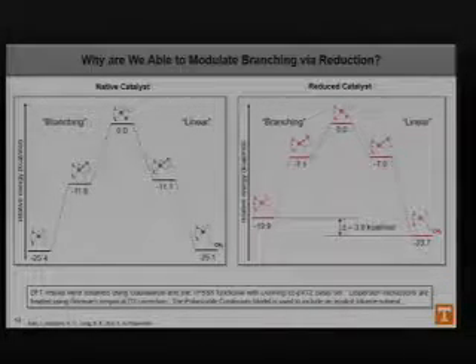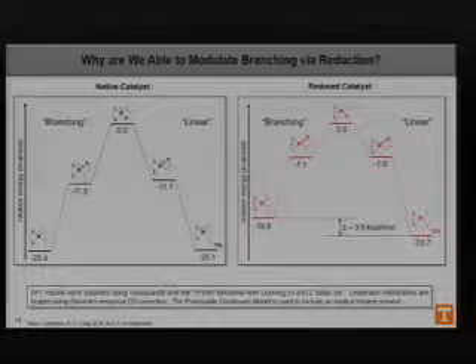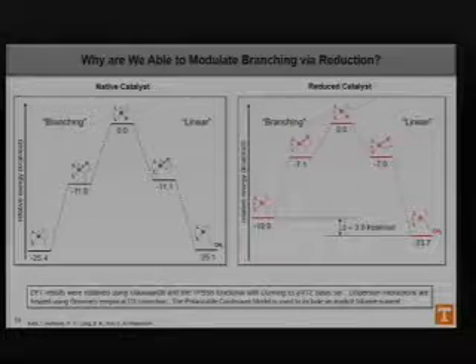However, in the reduced catalytic species, we actually found that it was negative 19.9 to negative 23.7. So it was actually 4 kcal lower in energy to go towards the linear pathway than it was to go towards the branching pathway. So we actually created the system in which it was more favorable to make the linear polymer.